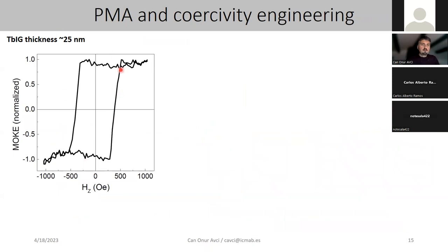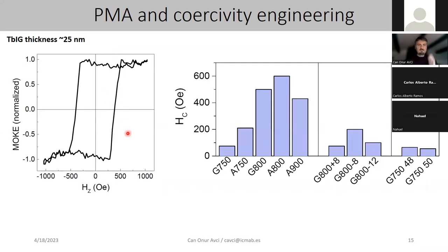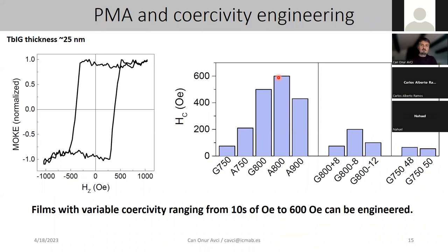And the typical magnetic characterization we have in the lab is basically using the polar MOKE. We can detect the magnetization reversal out of plane with an out of plane field sweep. And we see this typical 100% remanence signal with large coercivity. And if we measure all of the samples that we grew, you can see that we can tune the coercivity very effectively from tens of oersted to hundreds of oersted, 600 oersted. Which means that we can also change the anisotropy of the film very effectively.